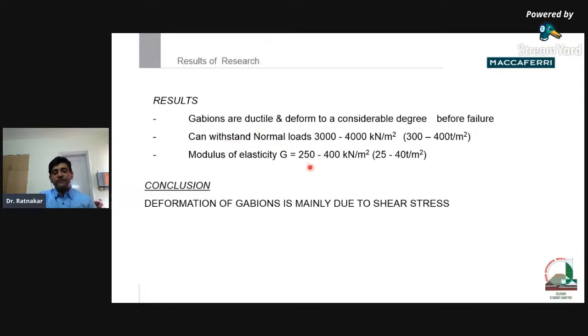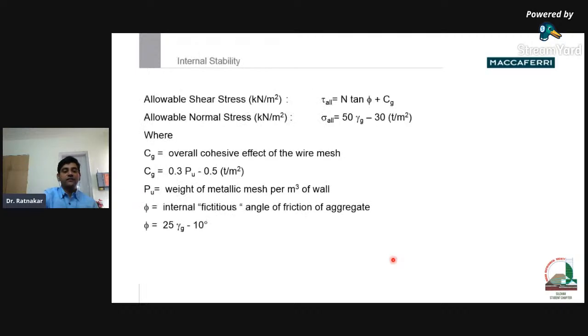So that's one observation. The gabions can withstand a normal load of 300 to 400 ton per square meter, and the modulus could be 25 to 40 ton per square meter. And more or less we observed the shear is the cause of the deformations of the gabions. The most important part when we do this analysis, we usually require two parameters, that is the cohesion and the friction angle.